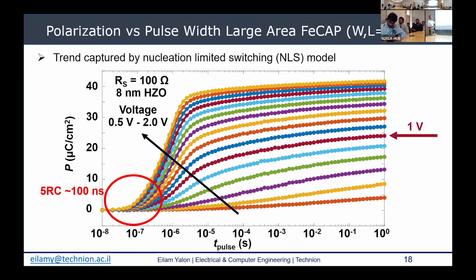switching kinetics. So what you see here is polarization versus time. Each marker here is a measurement, like I showed in the previous slide, with pulse width on the x-axis, and varying voltage amplitude, in this case between half a volt and 2 volts. So now we can get the full switching kinetics across a few orders of magnitude in time, and we can use that to feed our models and extract some information.